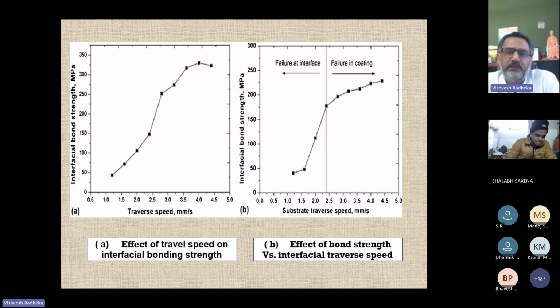And this is something very interesting from a metallurgical perspective. Focus on this particular graph: as the traverse speed increases, you see that the interfacial bond strength also increases. The higher the traverse speed, the higher the interfacial bonding strength, and at a higher speed the failure is in the coating. If you go with a lower traverse speed, you are putting in a lot of heat, and since you are putting in a lot of heat, a lot of intermetallics will form. Because of the extra heat, the failure is at the interface. So you need to improve your travel speed also, so that failure in the coating is achieved instead of failure at the interface. So travel speed is also very, very important.